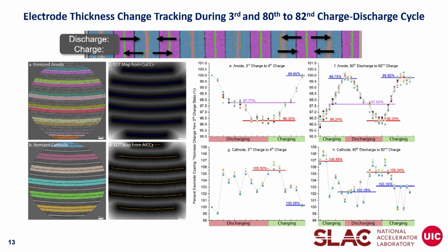We can see high reversibility even in the 80th to 82nd charge, even though at this point in the battery, we only have 80% of the original capacity remaining. Something really interesting and confirmation of the resolution of this type of measurement is that we see these dilation plateaus. And this is confirmed in the externally measured dilatometry experiments using a graphite anode.